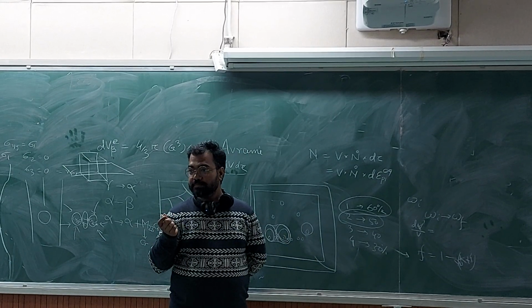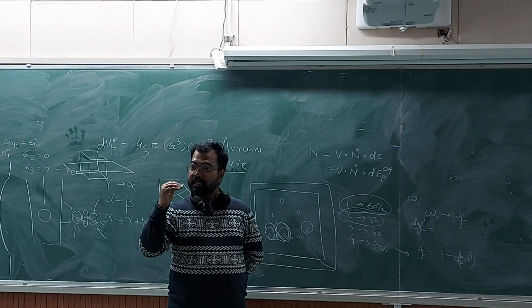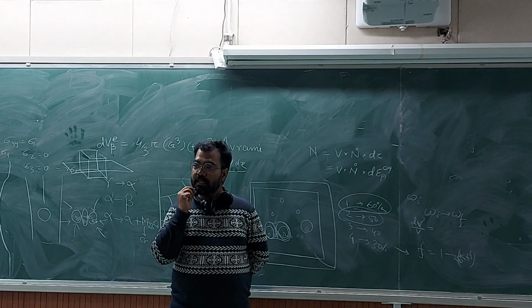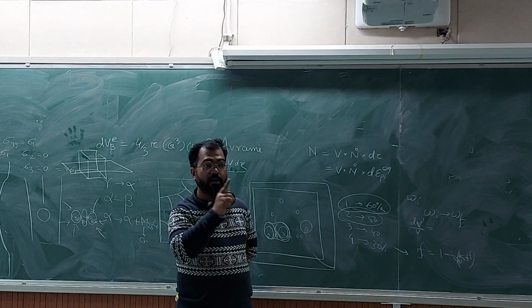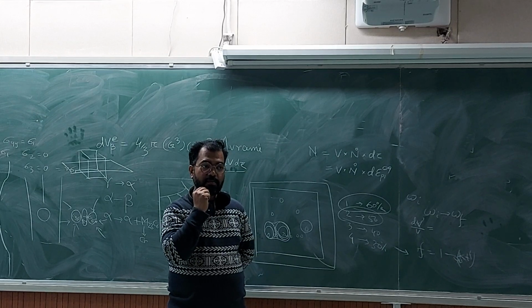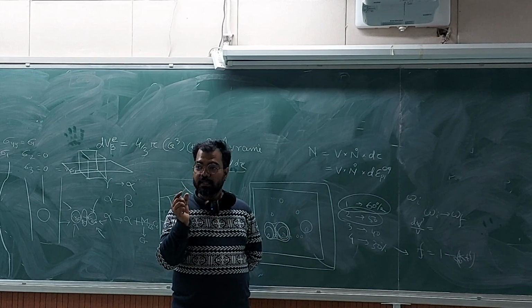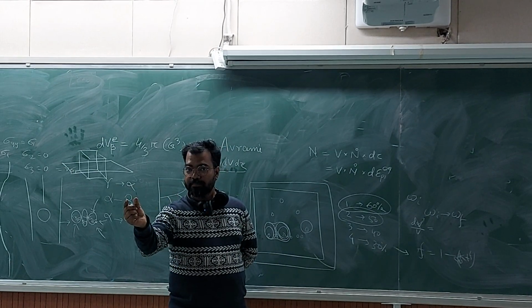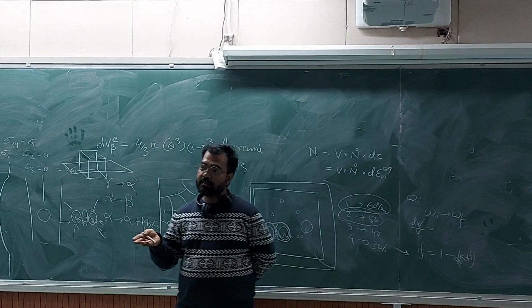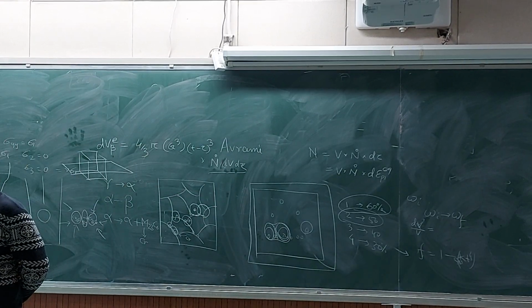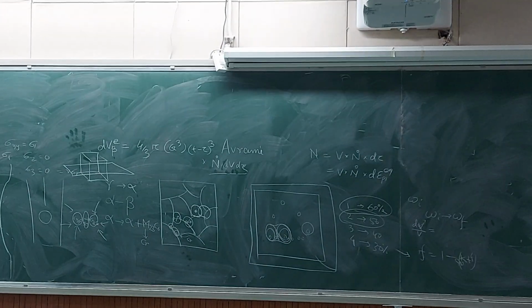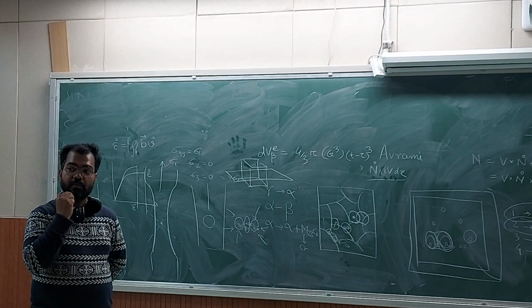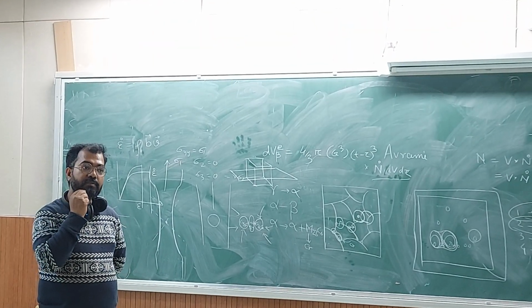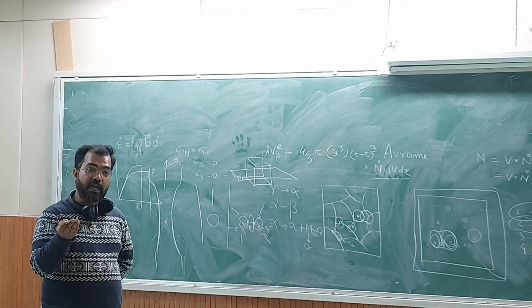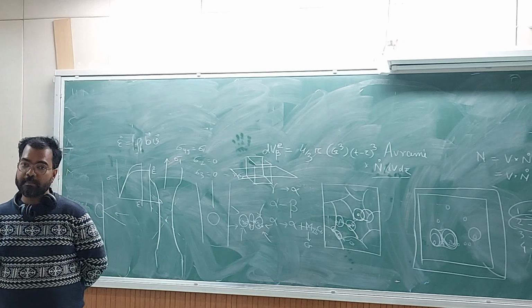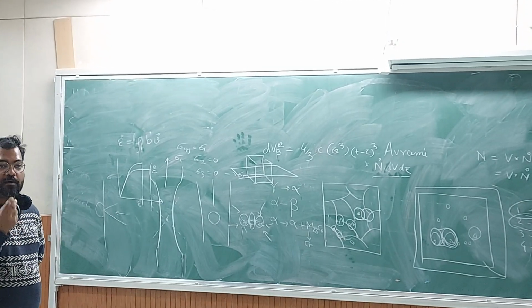When the temperature increases, the energy barrier will decrease, because the vibration of the atoms will increase, the thermal energy of the atoms will increase, and they will make longer jumps in every direction, right? So now the atoms have the ability to jump a longer distance, and that is why even on lesser packed planes you can have slipping. So this is why with change in temperature you will have more slip systems getting activated. This will not happen in FCC because there is no plane which has more packing fraction than 111. There cannot be a higher packing fraction than that. Okay.